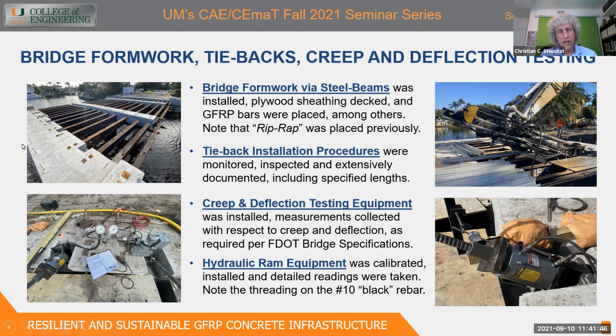A requirement for the DOT is that the seawalls and end bends, or the end sections on each of the ends, get tested. Since we had tiebacks. Tiebacks, for lack of better words, in this case, were diagonally 40 to 60 feet long installed systems that would tie back the end bends, preventing the walls from moving outwards towards the water side. On the top right, you can see the specialized rig, which drilled these in and grouted them, but then I was able to record some data.